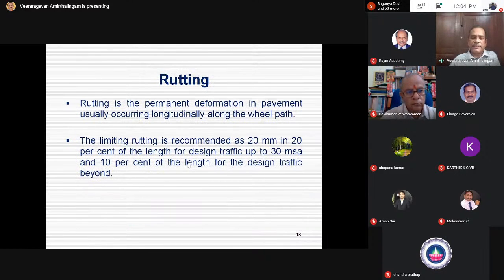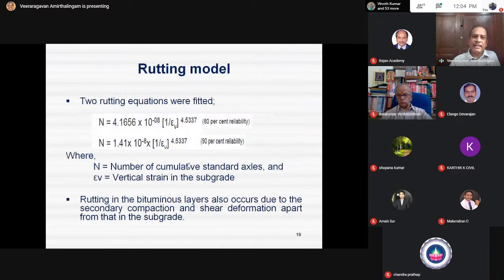Similarly, IRC has come out with a rutting model. So it again says 20 millimeter as the allowable rutting up to 30 MSA, and 10% of the length of the section can have this much of rutting. Again, they have given a rutting model as per IRC 37 2018. They have given again two equations, one with a higher reliability, other with a lower reliability. Well, so they consider rutting in this equation.